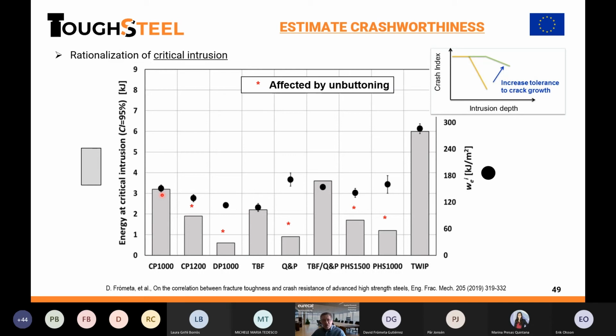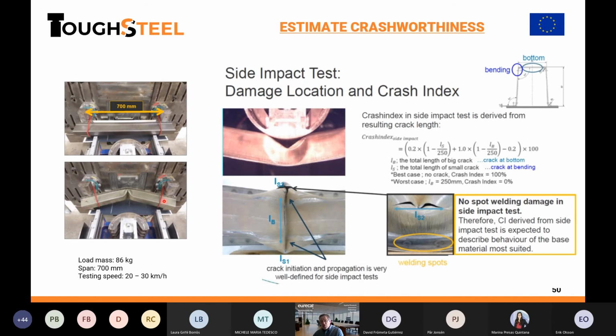But in the ones where the crack starts from the material, we see that the energy at critical intrusion is very similar, consistent with the essential work of fracture at the initiation of the crack. For complex phase, for TBF, for this mixed microstructure, for TRIP steels, this relation between the initiation and the energy is consistent. So again, understanding what is happening, you can have tools to measure it by fracture mechanics.